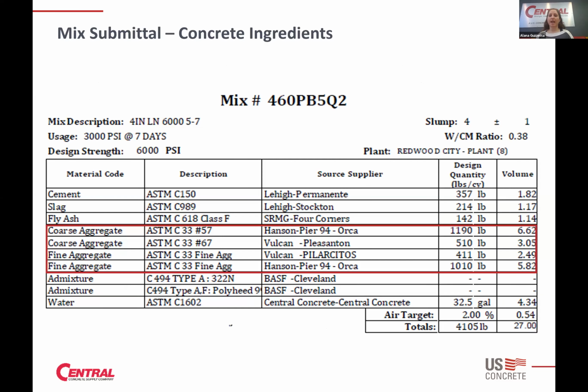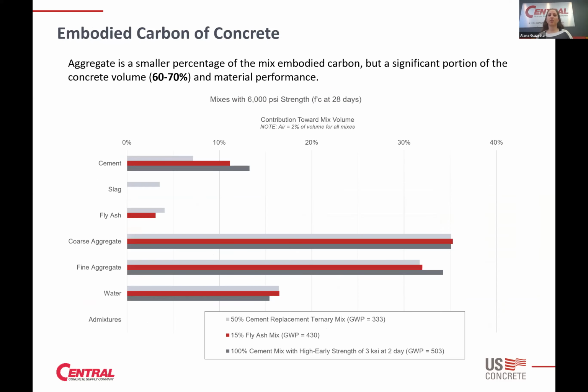So then next piece is the aggregates, the rock and the sand in the mix. And so if you go to this chart, this takes a look at a volume breakdown. So typical unit measurement for concrete is cubic yard. And so if you divide up that cubic yard by all the different constituents that are in it, you're going to find that about 60 to 70% of volume is made up of your aggregates, your coarse and your fine together. And so while cement is a significant portion of the embodied carbon, the aggregate is a significant actual product in your concrete mix. And so it plays a very important role as well in lowering the embodied carbon of your concrete.